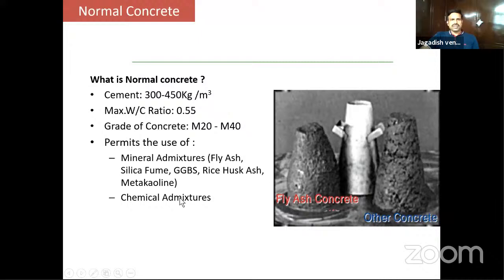And the maximum water cement ratio you see is 0.55, with grade of concrete between M20 to M40, and IS permits you to use mineral admixtures and chemical admixtures. The most commonly used mineral admixtures in India are fly ash, GGBS, and silica fume, and in little quantity rice husk ash, metakaolin, but in large quantities, most of the sites use fly ash and GGBS. And chemical admixtures, they use normal plasticizers, super plasticizers, retarders, accelerators, and so on.